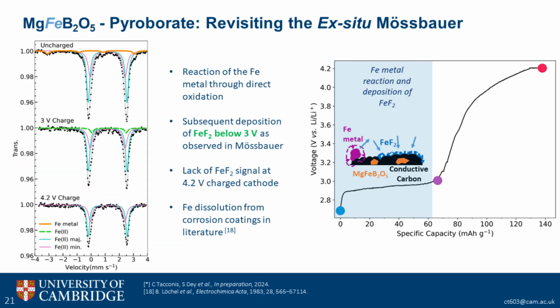If you remember, there was this additional 2+ peak at the 3-volt charge. And this green Mossbauer signal ended up being consistent with iron fluoride. And so what we think is happening to our iron metal is that it is reacting out through proton attack. It's then depositing into iron fluoride below the 3-volt, as we know from the literature. But then we don't see it at the charge again.